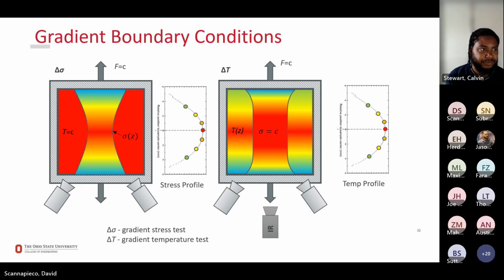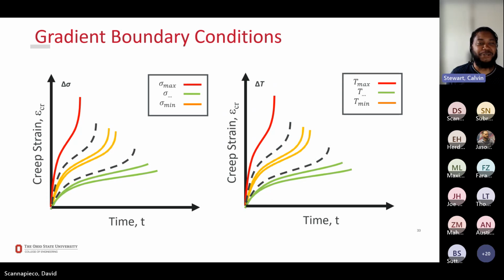Next slide. And I think this one, okay, there we go. So this is what you end up with. If you have a symmetric boundary condition, you can get replicate testing. So like sigma min, you see we have two curves there because there's two points at minimum stress, right? And so from one sample, you literally get as many curves as you want. The dotted line means as many as you are able to get through your optics, right? As many individual strain gauges along that sample that you can pull. Next slide.